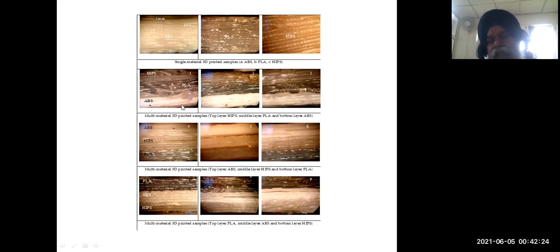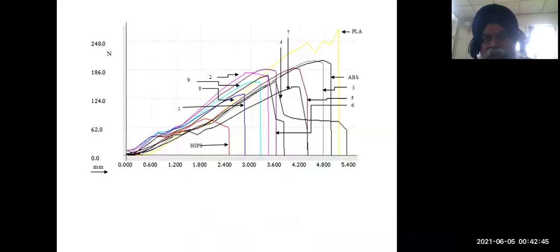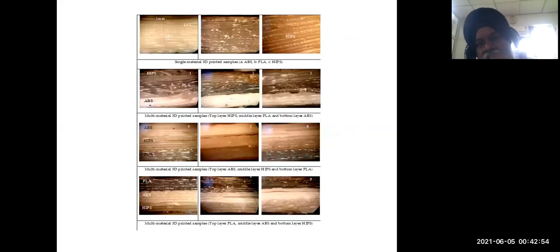Basically, the reason is the difference in the Tg, glass transition temperature, of PLA and ABS. So if I am taking a lower layer of ABS, then putting a layer of PLA, this material is actually spilling out. Basically, this microstructure clearly justifies that if I print this component at this setting, it must have low mechanical properties. We can actually correlate with the stress strain curve. You can see in curve one, I am getting the lowest area of triangle. So modulus of toughness will be less in this case. So basically, we tried to correlate the microstructure with the mechanical property, right? And we can basically justify which material I should put in the lower one, which in the middle, and which in the top one.